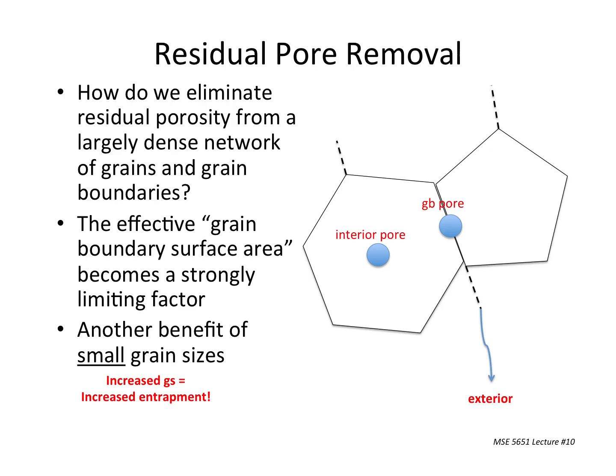And so then we have to think about, well, if we do get grains with pores inside them, interior pores versus grain boundary pores, again, as I said, if these two pores are sitting there and we come back later, you'll see the grain boundary pores gone because they diffused to the surface along that pipeline to the surface, as I always like to call it, to give you a clear idea of just how efficient it is versus the interior pore, which might still be sitting there in the same microstructure. All right, because it's stuck with just slow volumetric diffusion.